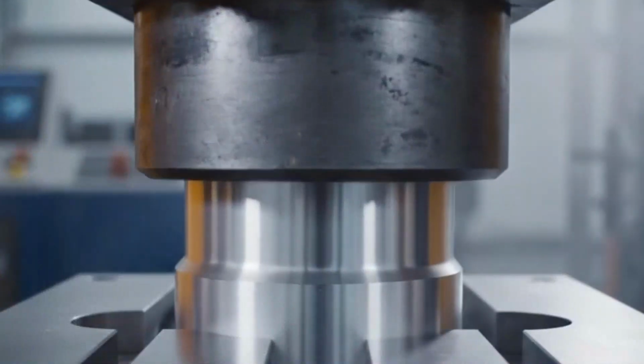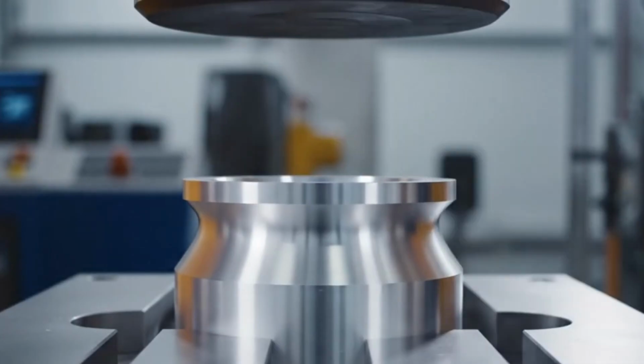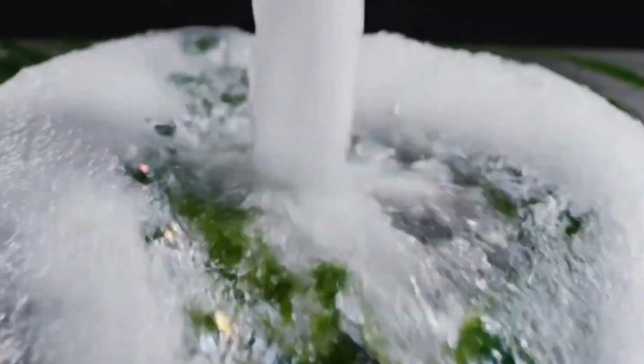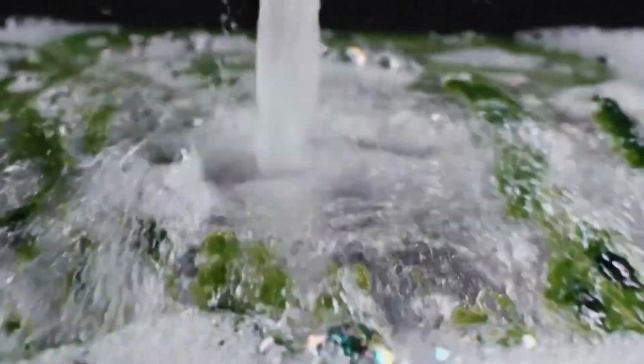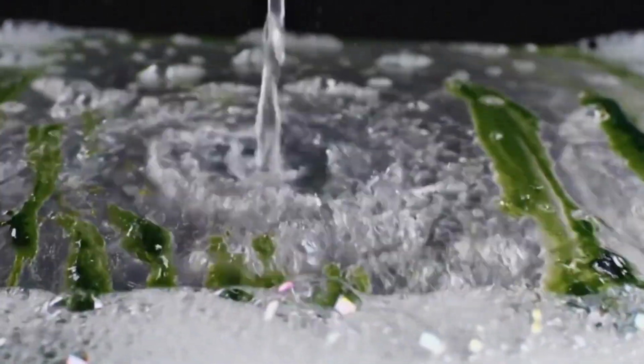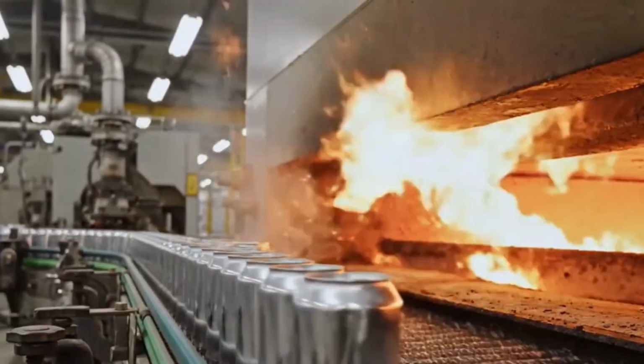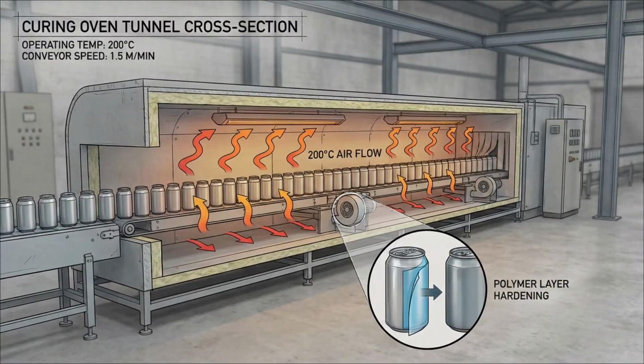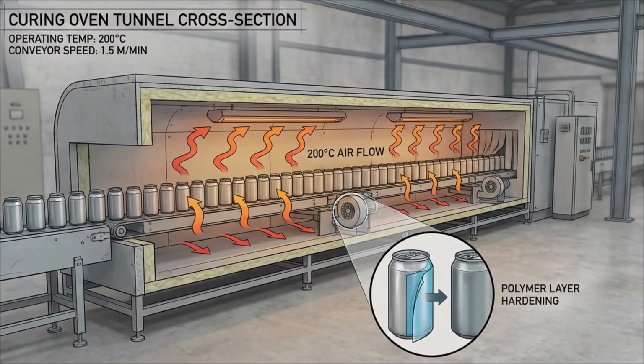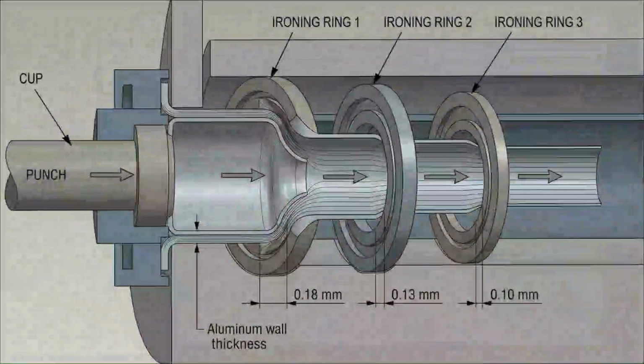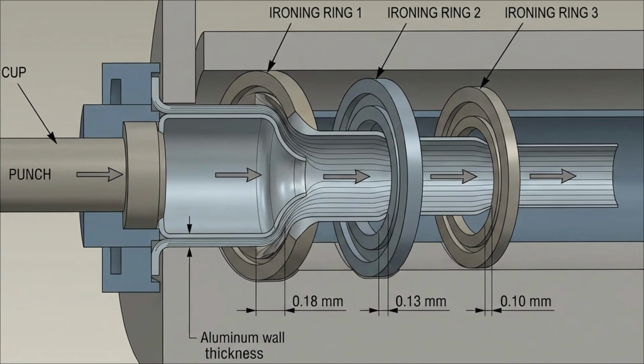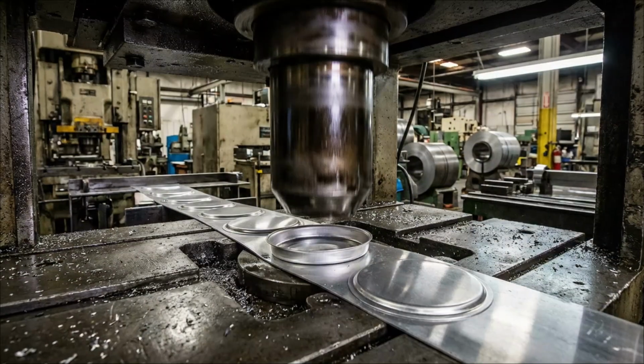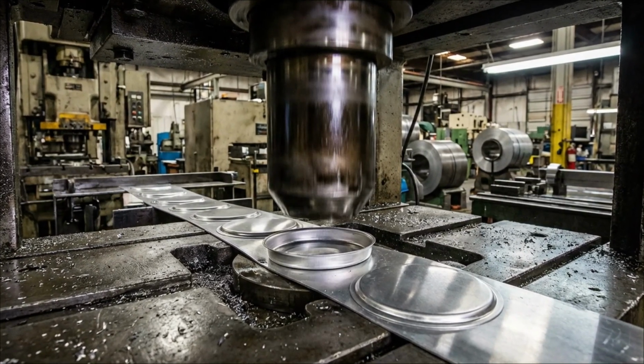The cup enters the body maker, the heart of the line. A hardened punch drives it through 3 ironing rings, thinning the walls from 0.28 to around 0.10 millimeters. The aluminum stretches over 400%, but must remain perfectly smooth. If punch temperature rises by 10 degrees Celsius, the metal softens and dimensions drift. If friction spikes, the can tears instantly. This 2-second sequence sets 80% of the final geometry.